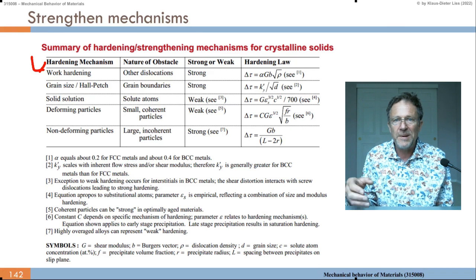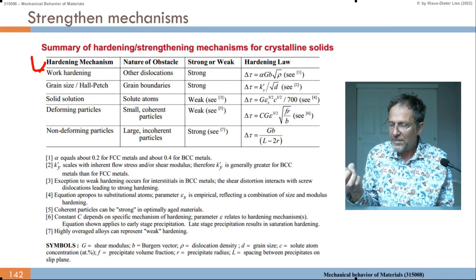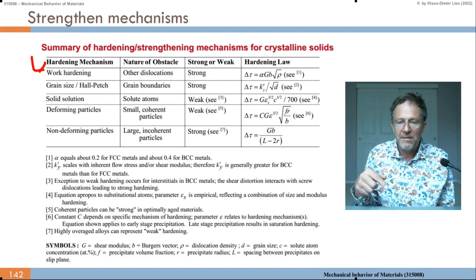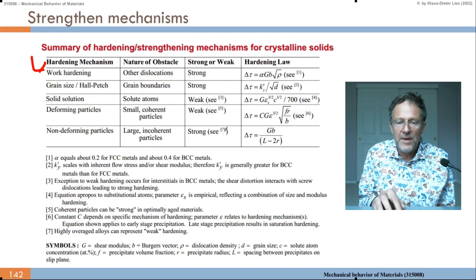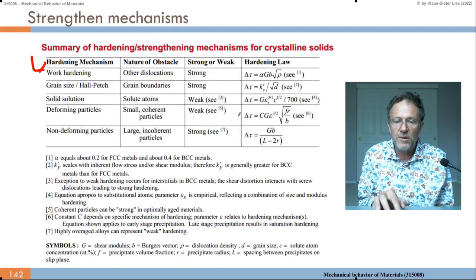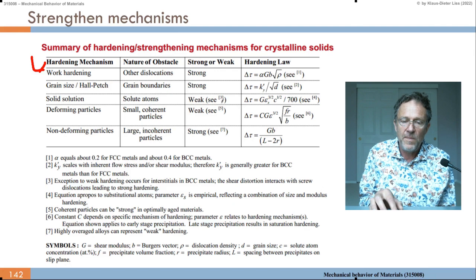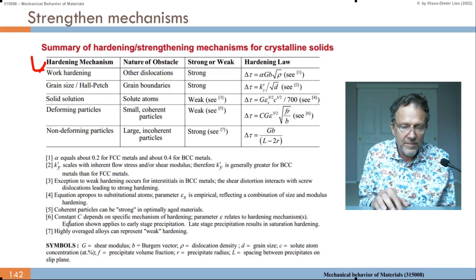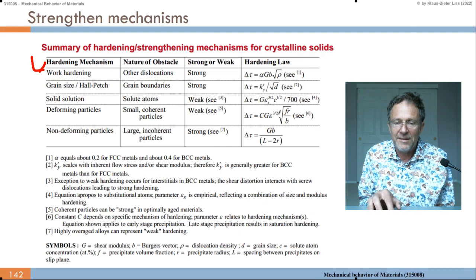In diffusion, we know when we have displacement, there's this coherence factor that the vacancy wants to go back to the original location because of the strain field, which has to move with the solute atom, or the other way around. If there's a solute atom, then it interacts with an applied stress field. And that can be described by delta tau becomes C, a constant that depends on specific mechanisms, times the shear modulus, strain to the 3/2, and then the square root of F r over b. So F is the precipitate volume fraction, r the precipitate radius.